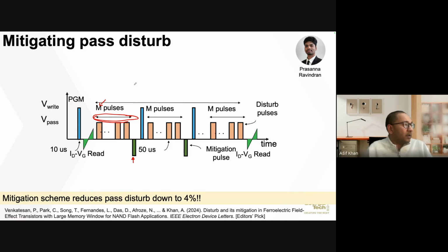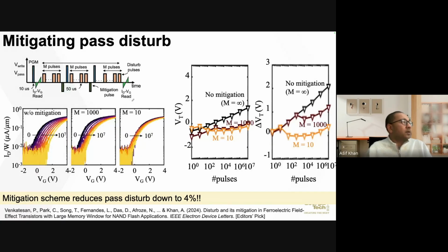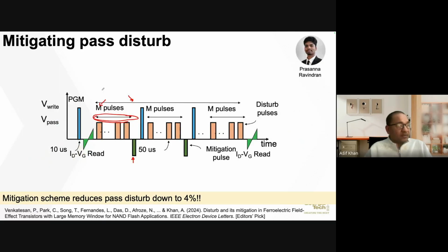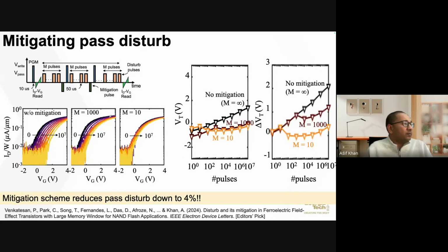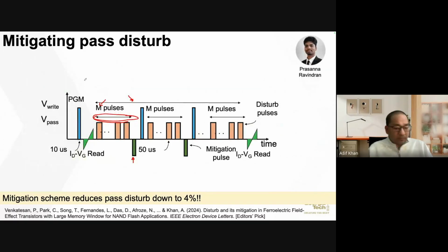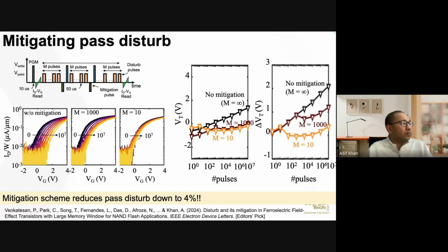And he then used this pulsing scheme and applied it on our devices. With this pulsing scheme, what we could see is that if we tune the frequency of this refresh pulse, we can actually remove the disturb effect. What he was able to show is that without any mitigation scheme, the disturb can be as high as 25% or so, but with a proper mitigation scheme, this disturb can be lowered to below 5%. All right, and this was published last year in EDL.